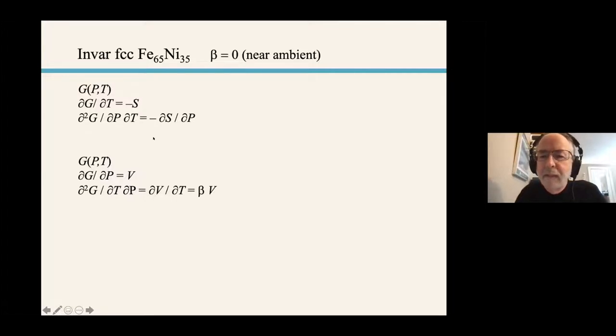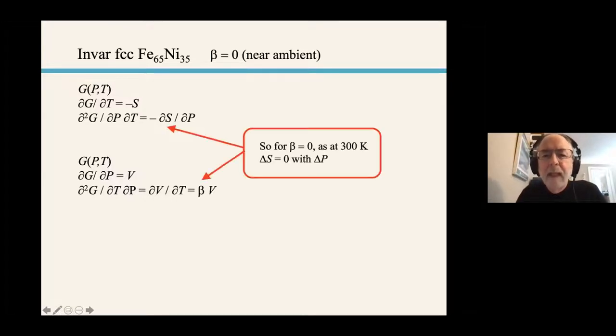Now, this gets to the method behind our experiments. Invar has zero thermal expansion, so it must have no change in its entropy with pressure. Doesn't mean all of the pieces of the entropy are going to be pressure independent, but somehow the total has to be equal to zero as we vary pressure over 4 gigapascals, which is in that Invar range. So what are the pieces that sum to zero?